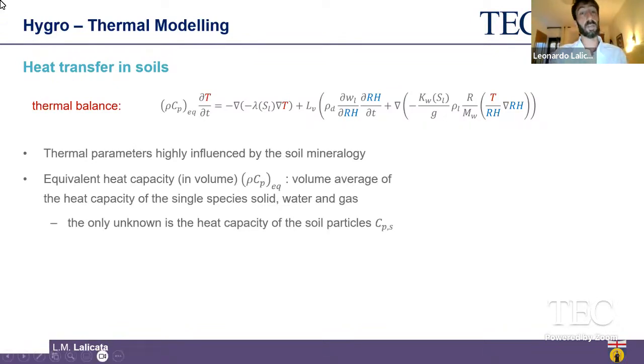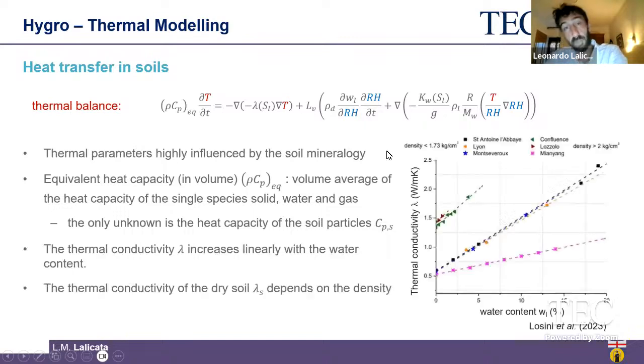But for instance, the equivalent heat capacity of our domain, which includes the soil, the water, and the air, is nothing but a volume average of the heat capacity of the single species, such as solid, water, and gas in our domain, which means that the only unknown is the heat capacity of the solid particles, this parameter CPS here. On the contrary, the thermal conductivity, lambda, which again is a function of the amount of water we have in our model, is observed from experimental data.